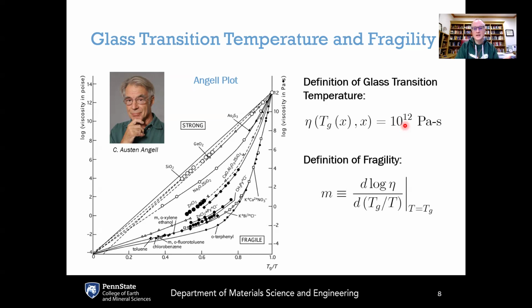But if you are at lower temperatures, which causes the viscosity to be higher than 10^12 Pascal seconds, then that flow is so slow that you are kind of crossing over into more solid-like behavior. So this first definition here is the glass transition temperature, and that is defined as the temperature at which the viscosity of the liquid is 10^12 Pascal seconds.